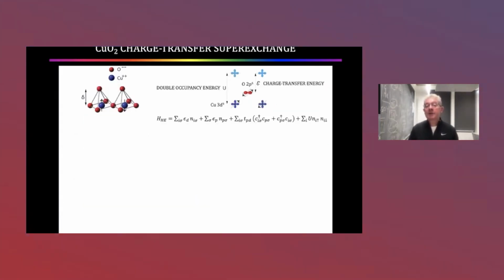All right, now let's turn our attention to superexchange. And here I'm not talking about a crystal, I'm just talking about 3 atoms, 2 copper atoms in the 3d9 state and 1 oxygen atom bridging them in the 2p6 state. You can write the Hamiltonian for those 4 electrons. And if you know what you're doing, you could diagonalize it, but it's relatively easy to solve in perturbation theory. So you write the energy of the d states, you write the energy of the p states, you write the pd hopping rate, and then you destroy a p and create a d, or vice versa. And you write the Hubbard energy on the two copper sites, Hubbard energy U. So that simple Hamiltonian you can study.